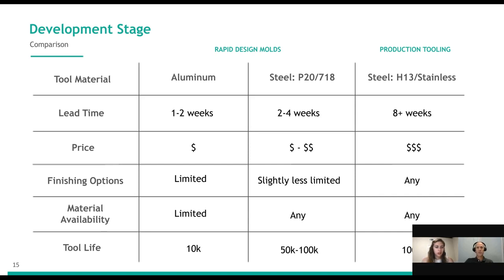Again, another little chart that throws all the different options out there, allows you to see a quick breakdown, a comprehensive guide from all of our previous slides. One thing we haven't talked about too much yet is the finishing options. Why is this more limited for an aluminum tool? You're not able to polish aluminum like you can a steel tool. So a lot of times if you follow, which we do, the SPI standards, you're typically only able to achieve an SPI A3 polish on aluminum tools. So if you're needing something that's a high polish, you just can't quite get that with aluminum.